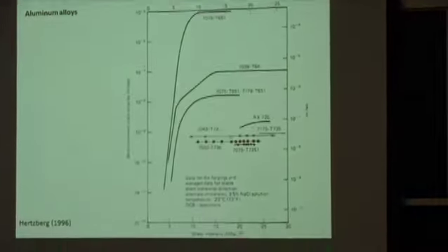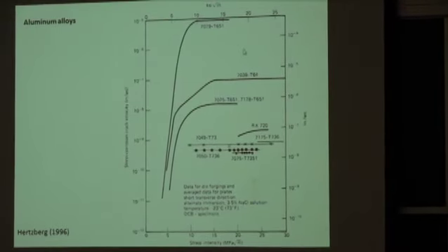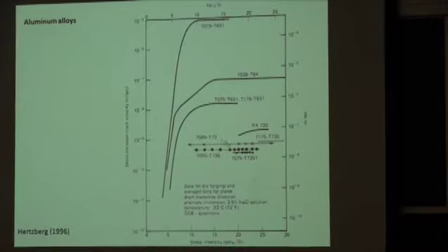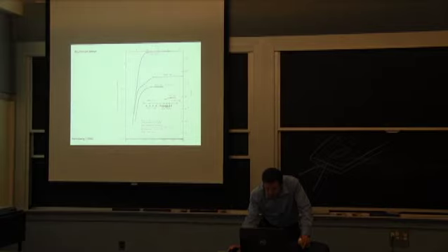Last thing about aluminum alloy, I mentioned that it is sensitive to stress corrosion cracking. This plot is intended to show for the 7000 series how different the stress corrosion cracking is between a peak aging, so highest yield strength, and an overage situation. These are fairly similar alloy. These are all overage. It's a T7 as opposed to a T6. What you're looking at for the vertical is the stress corrosion crack velocity. So we have a change by 5 orders of magnitude on how fast the stress corrosion crack is going to grow.